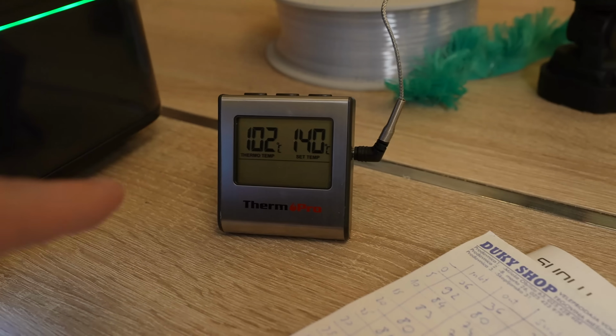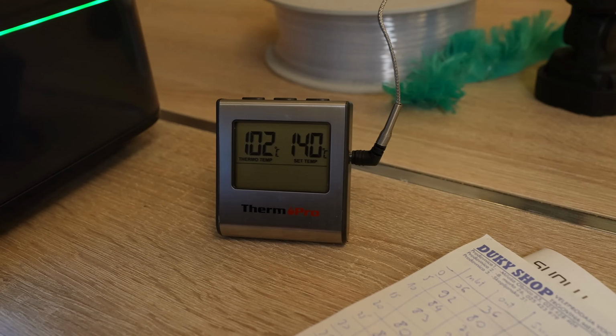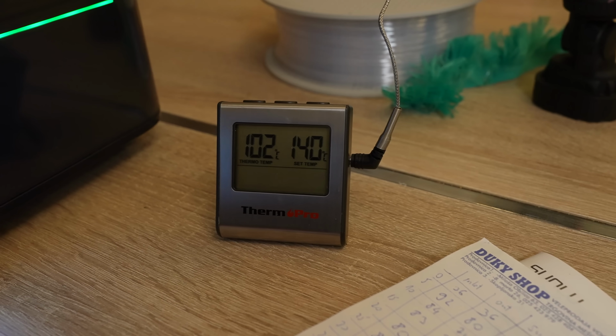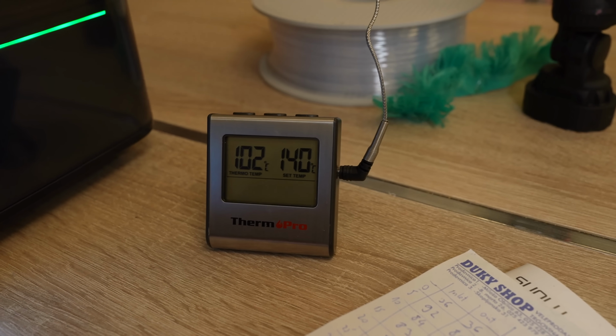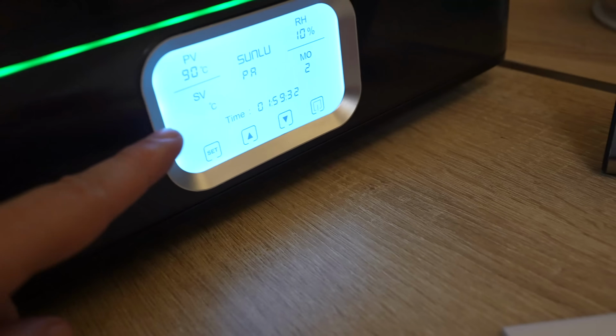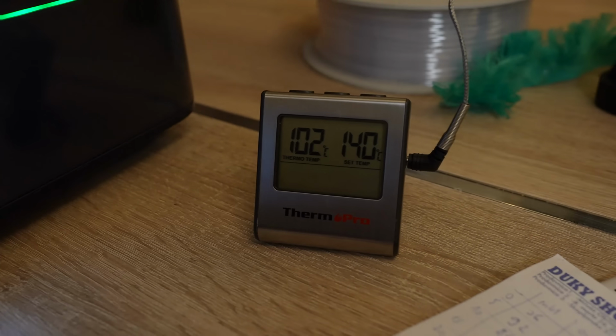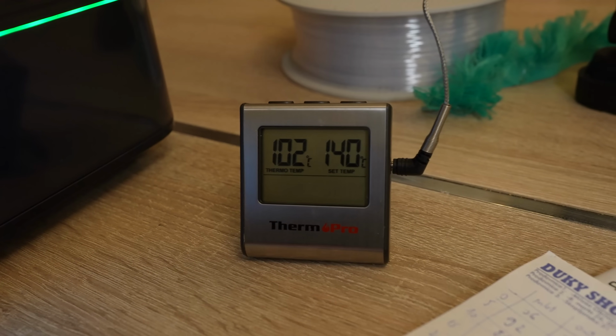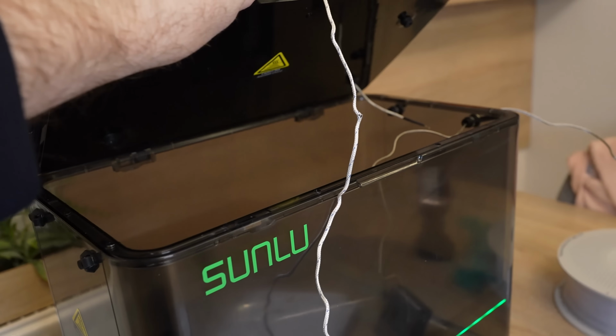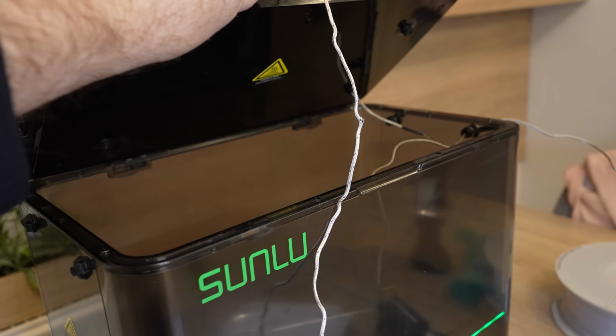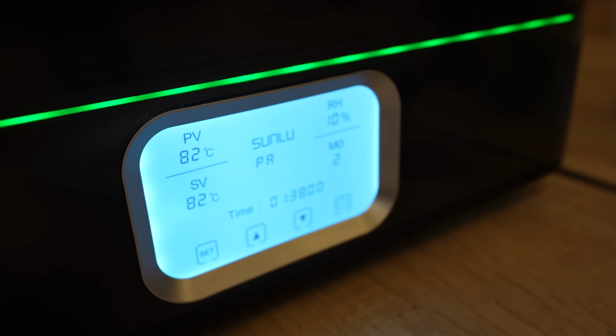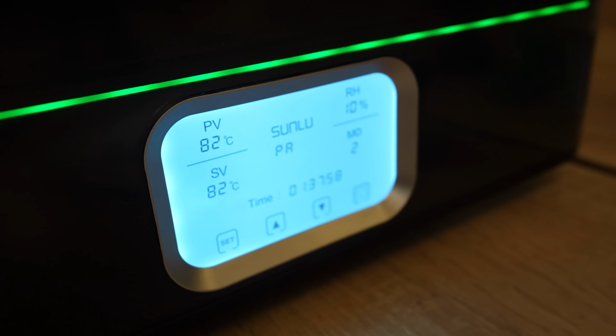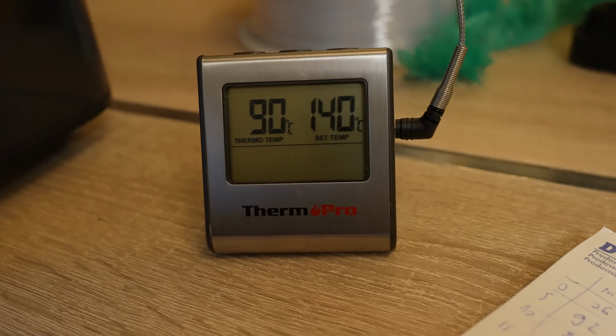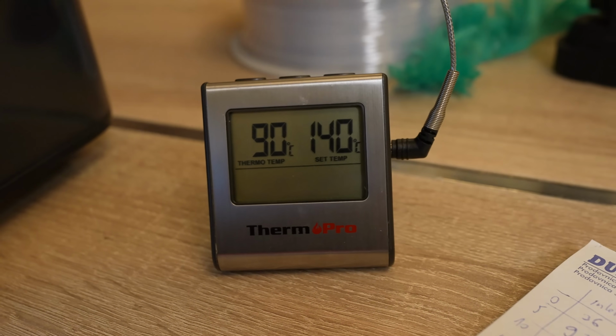So looks like the annealing temperature stabilized around 102 degrees Celsius, but I need 90, this is what I usually use. So I'm curious if I set it to 80 degrees Celsius, whether I will get those 90 degrees Celsius approximately. I will open it a little bit to speed up the process. A little jump in the time. Only when I set it to 82 degrees Celsius, then it stabilized, the annealing temperature is 90 degrees Celsius.